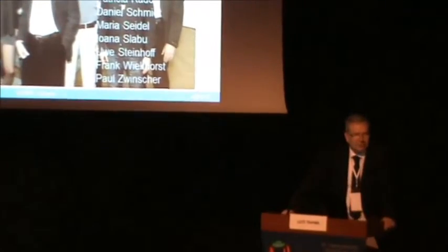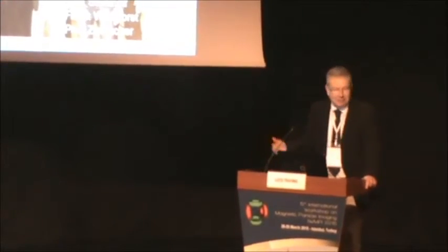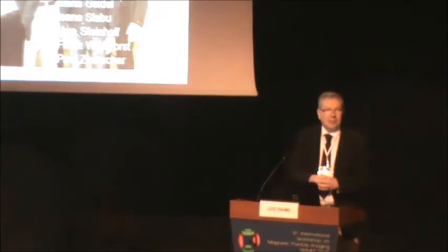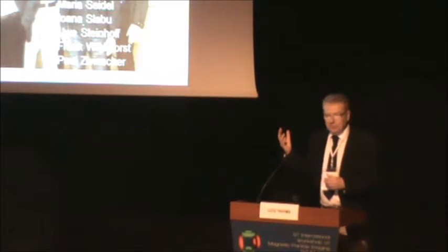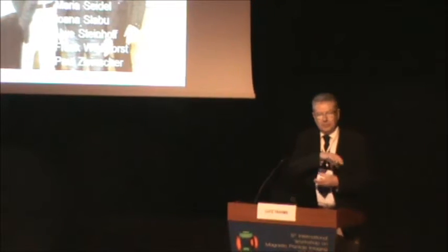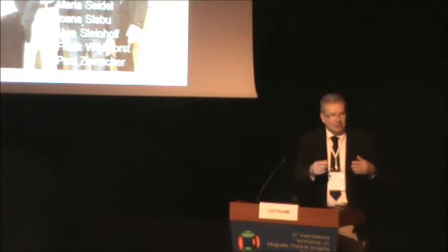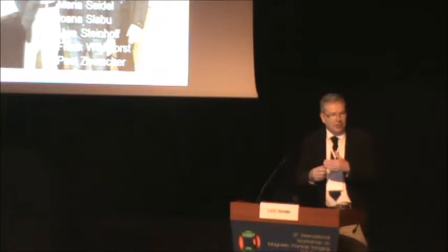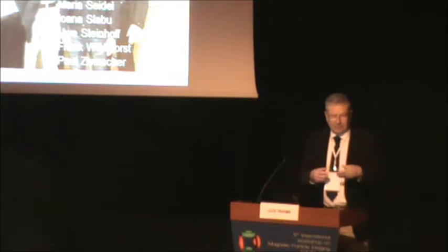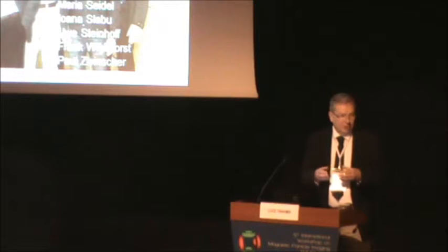Okay, that's a very good question, and in fact this is a challenge. In earlier years we just did not use strong fields, so we didn't apply millitesla but only microtesla. That was the beginning, of course. The next step was that we used a setup different from what I have shown you, and we turned the sample around so that the magnetic field is not directed into the SQUID, so that the stray field of this magnetizing field is 2 orders of magnitude lower than the stray field at the sample.